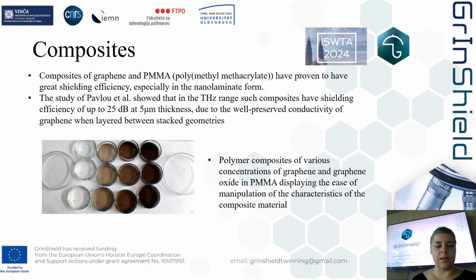And in this study by Pavlu, they showed that in the terahertz range, such composites have shielding efficiency of up to 25 decibels at 5 micrometer thicknesses. And we have created some preliminary composites of various concentrations of graphene and graphene oxide in PMMA, which display the ease of manipulation and characteristics of this composite material.